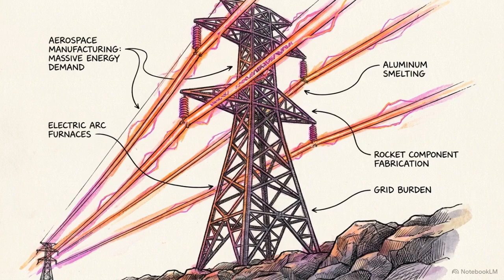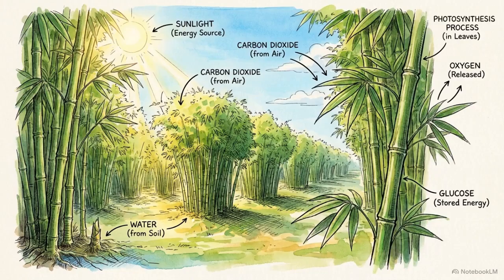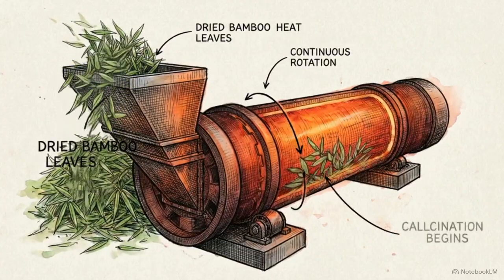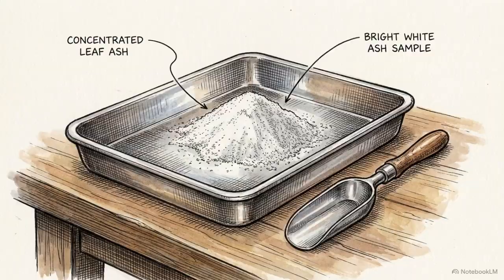To extract this biogenic silica, the bamboo leaves are harvested and calcined at 600 to 800 degrees Celsius to burn away the organic material. What remains is a concentrated leaf ash containing an exceptionally high 75 to 82% silica. Laboratory analyses confirm this precise sequence consistently yields a final product with 98 to 99.7% purity, satisfying current aerospace tolerances.